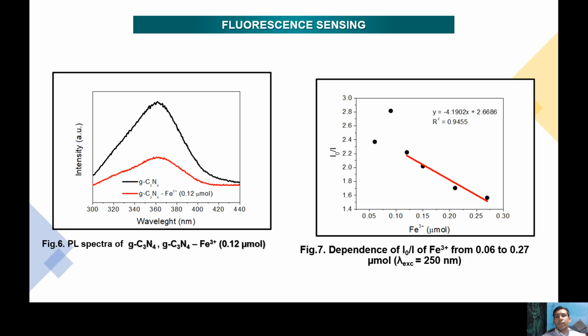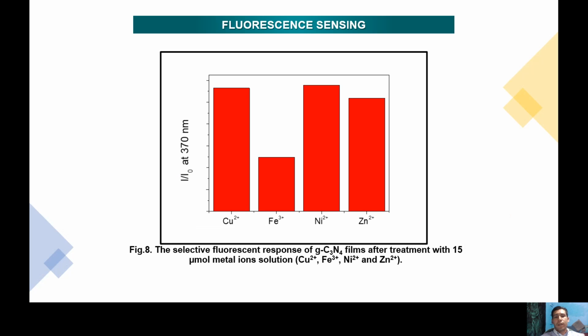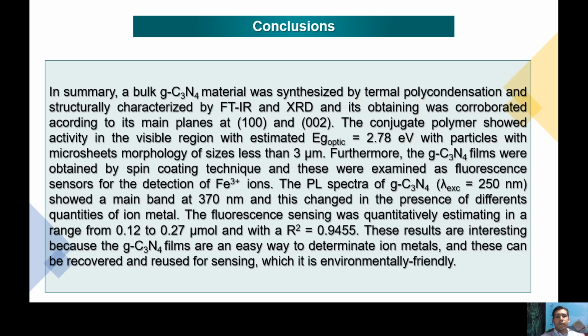For the first points we lose the linearity, but for the last points we can find a good linear correlation, and the coefficient of determination is equal to 0.9455, and this range corresponds to 0.12 to 0.27 micromole. In this range we can find the quantities of the iron metal ion, and also we compare these values with the other metal ions, using the intensities at 370 nanometers, and we can find that the iron presents quenching.